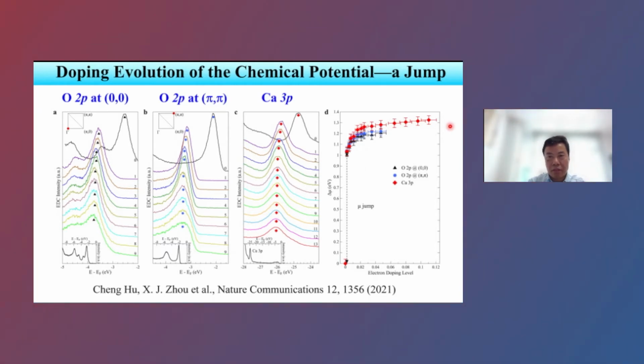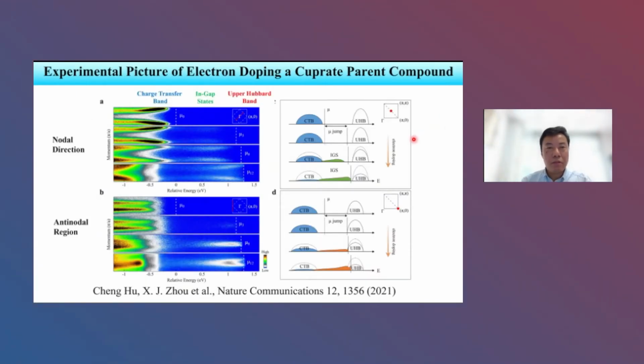So combining the chemical potential jump and the observed electronic structures, we can establish an experimental picture of electron doping cuprate parent compounds. So this is the summary of the results. You can put the chemical potential for different doping levels. Okay, for the parent compounds, chemical potential is here. When you dope electrons to the system a little bit, the chemical potential jumps to here, and keeps increasing. So you can really see the charge transfer band. The charge transfer band at the beginning is very strong and becomes weaker. Eventually it disappears. And the in-gap states from the beginning zero gradually increase and eventually become very strong. It is the same case for the pi-0 region. So then we get some experimental picture of doping the Mott insulator.